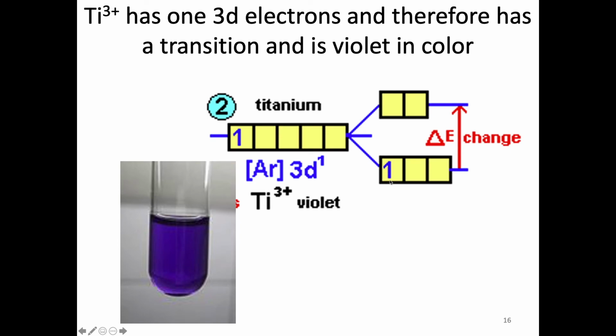And what happens here is, again, if we hit this material with some type of wavelength of energy, we can basically promote this electron, right? This electron becomes energized and can jump the gap to one of the other energy states, right? So this electron can basically transition to one of these sites, and that has a specific energy level based on the material and the transition that we have here. And so that specific change in energy would result in the energy corresponding to a particular wavelength.